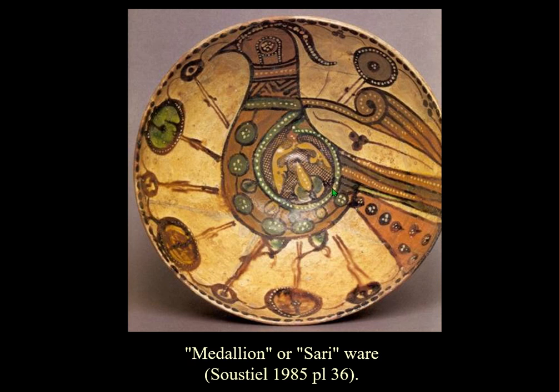What is known in the literature as Sari ware is associated with the town of Sari. I call it medallion ware because it's a very distinctive style, and it isn't necessarily made at Sari — in fact it's made in other centers, certainly in southern Iran. It has these medallion styles all over it — little round things, big round things — and the white dots on the black lines particularly distinguish it, or green bands. Basically white dots, slip painted, lead glaze make this quite a distinctive style.